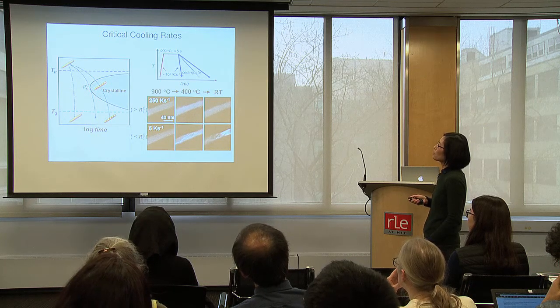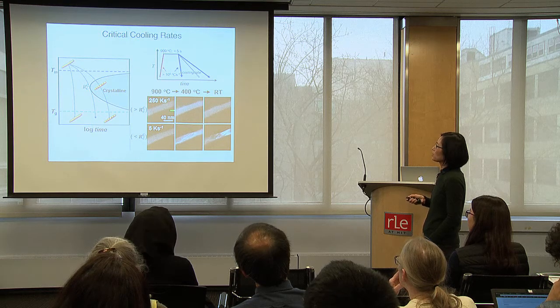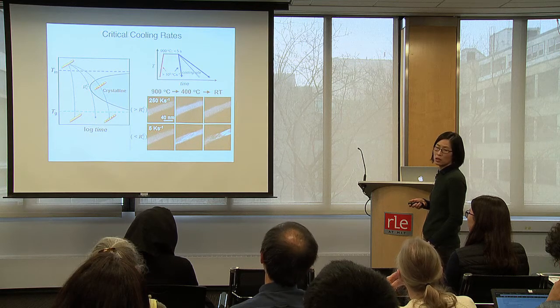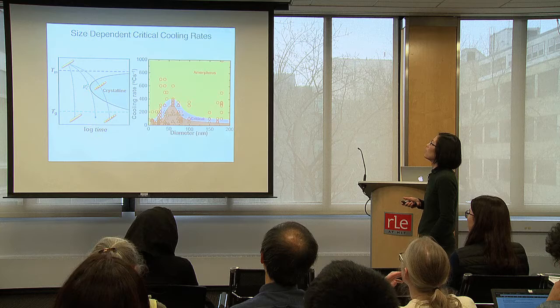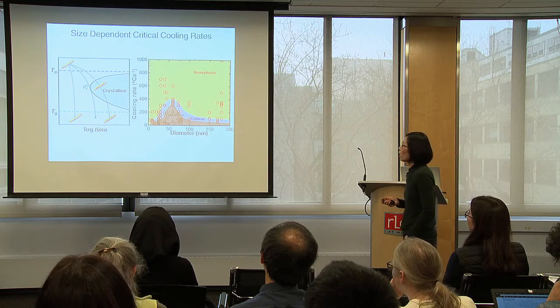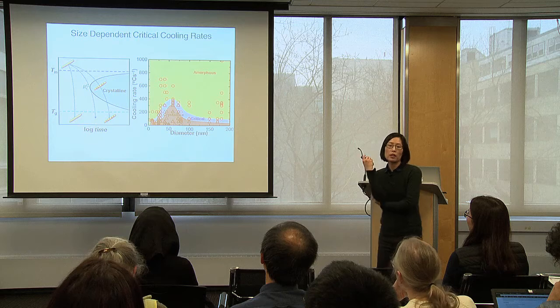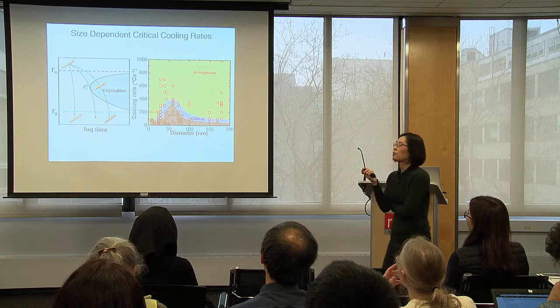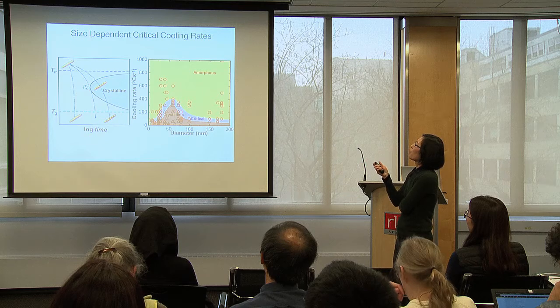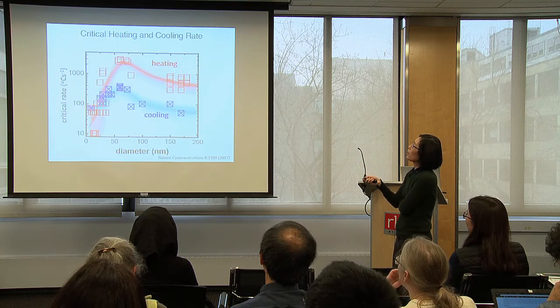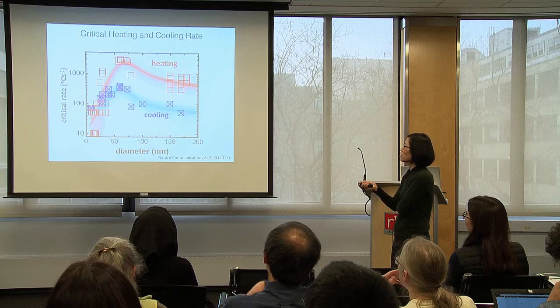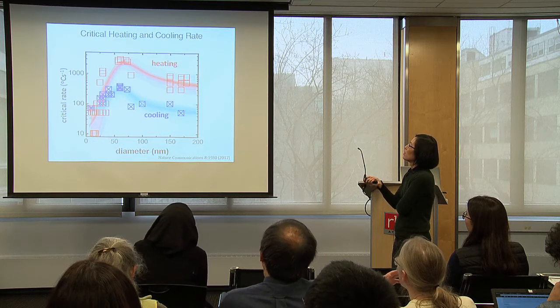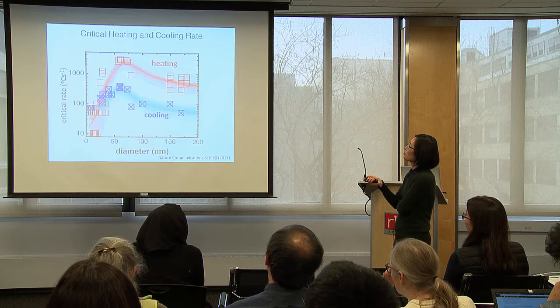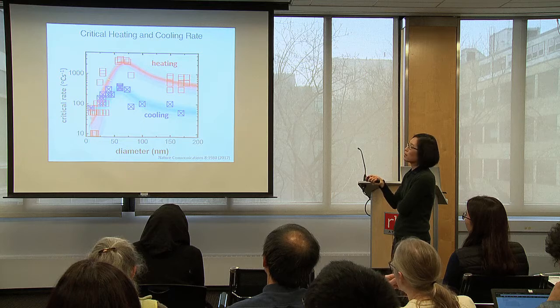Okay? So here's an example. When we cool it faster than the critical rate, at room temperature, you don't see any crystalline grains. If you cool it slower than the critical rate, then now you see the rods have crystallized. So here's the data. Okay, so again, it has this non-monotonic rate size dependence, as we would expect. So what we did is to overlay the critical heating rate and critical cooling rate together as a function of diameter. Okay? So you see that the critical heating rate is about 1 to 2 orders of magnitude higher than the critical cooling rate.